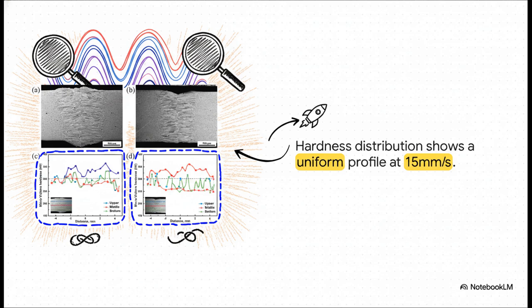Now, that drop is totally expected in welding, but take a really close look at the difference between the two. The 20 millimeters per second condition on the right shows a much more erratic, separated profile between the upper, middle, and bottom sections of the weld. But the 15 millimeters per second condition on the left is much more uniform. The thermal profile there preserved the mechanical properties in a vastly more balanced way.